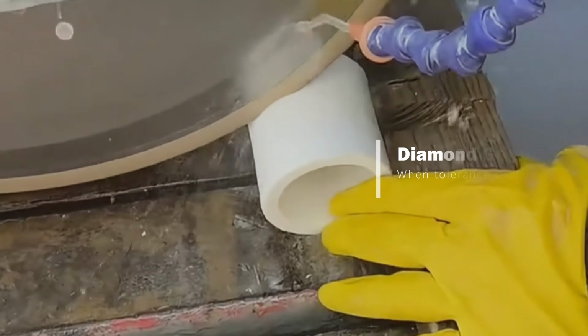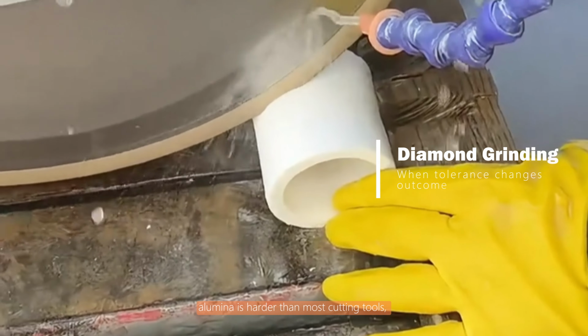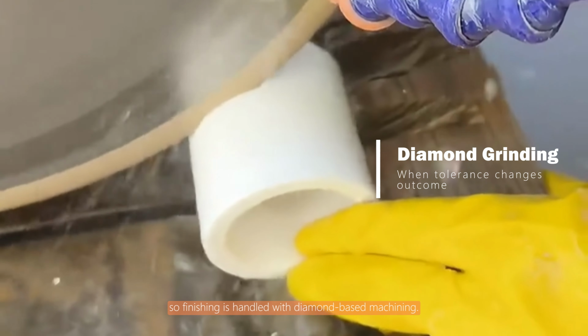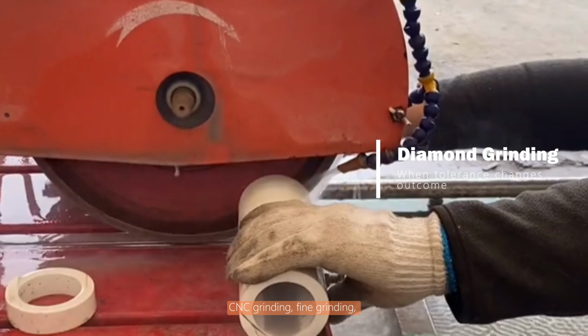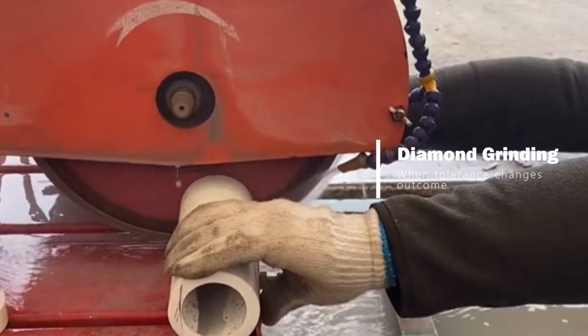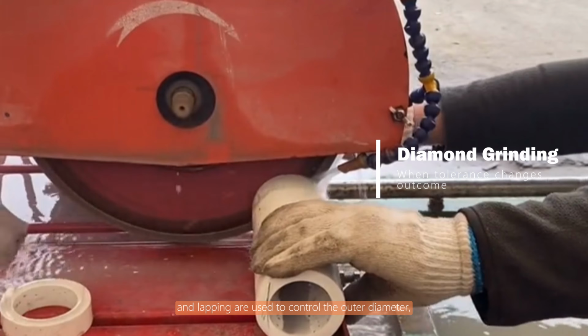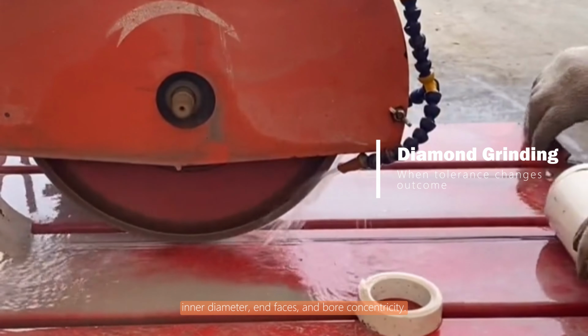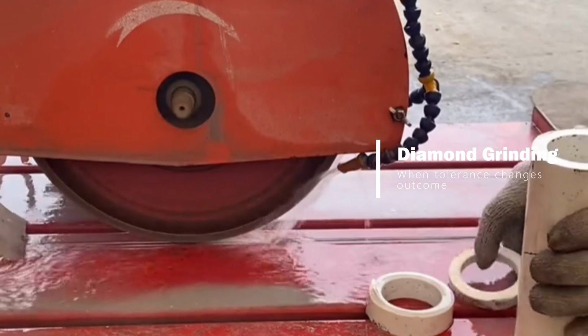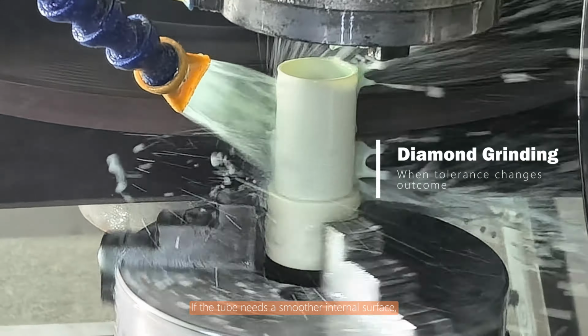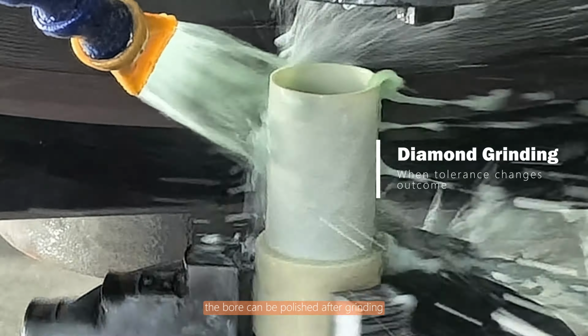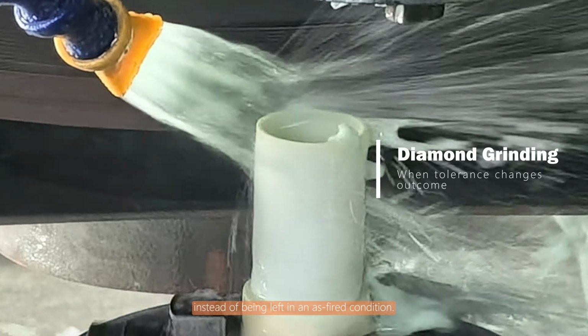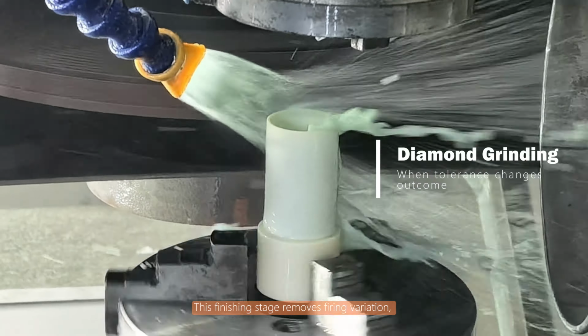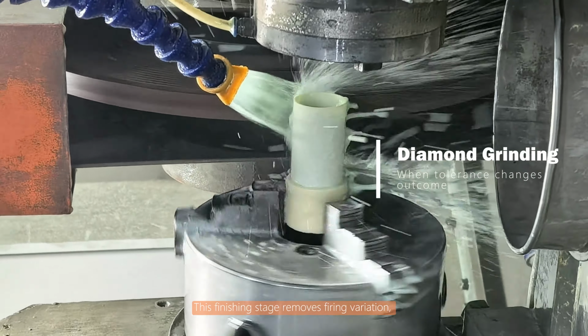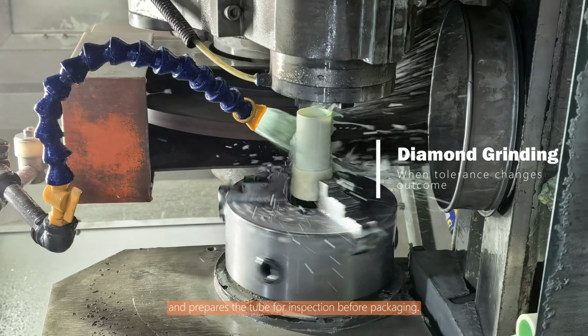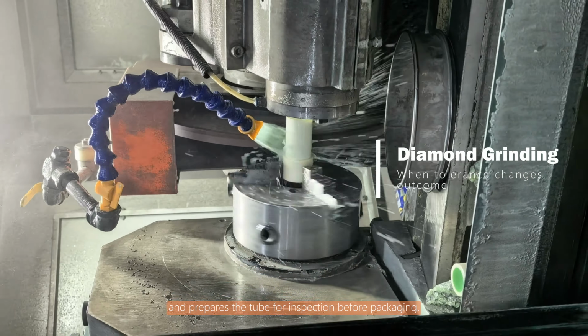After sintering, alumina is harder than most cutting tools, so finishing is handled with diamond-based machining. CNC grinding, fine grinding, and lapping are used to control the outer diameter, inner diameter, end faces, and bore concentricity. If the tube needs a smoother internal surface, the bore can be polished after grinding instead of being left in an as-fired condition. This finishing stage removes firing variation, corrects critical dimensions, and prepares the tube for inspection before packaging.